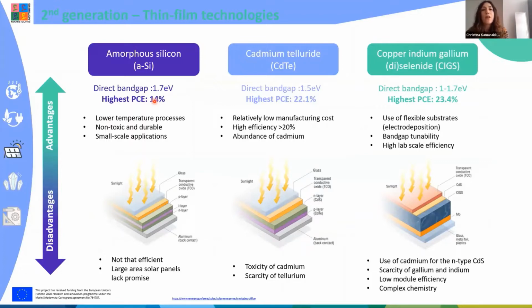However, amorphous silicon solar cells have been used in consumer electronics, like the old school calculators that we used to have back in the 90s, before they were substituted by our smartphones. Then we have cadmium telluride. Cadmium telluride has a direct bandgap of 1.5 eV and efficiency is up to 22%. Even though their manufacturing cost, the use of cadmium, which is toxic, and the scarcity of tellurium are the main drawbacks. And then we have copper, indium, gallium diselenide, or CIGS solar cells.